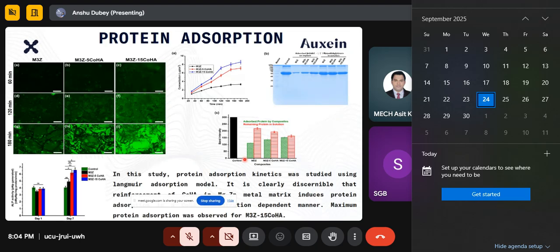So this is the major study which needs to be done for any implant, because if we don't know how the cell-material interaction is taking place, we cannot modify the designs of the implants, and we cannot study whether this is supporting the cells, because the bone-forming cells are osteoblasts, and whether the bone is growing or not. That's why we studied this protein adsorption. Here in this analysis, if you see this green color, we took various compositions, and the maximum happened for 15%, because the CoHA helped in more protein adsorption as compared to without HA and with 5% CoHA. CoHA means co-precipitated hydroxyapatite, which I showed in the previous slide.